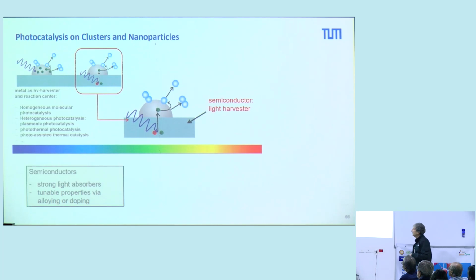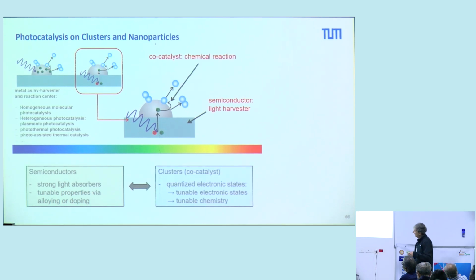That means in our system we have a semiconductor, in this case titanium dioxide, which is the light harvester. And then we have a co-catalyst, and these are our platinum clusters. The role we have to determine is what happens on these clusters. On the semiconductor, you can of course tune, you can dope these semiconductor materials, you can change the band gap, you can somehow influence the positions of the lower and upper edge of the conduction and valence band. So you have tuning parameters to change the optical properties of these semiconductors.